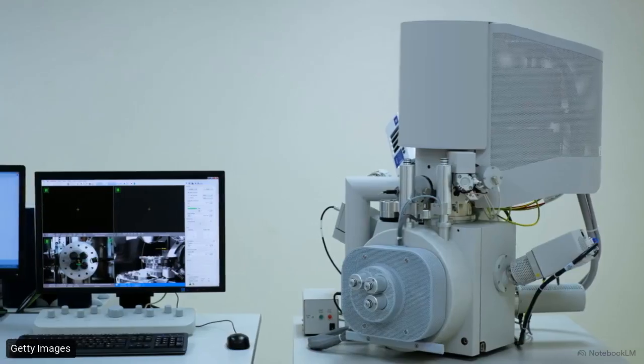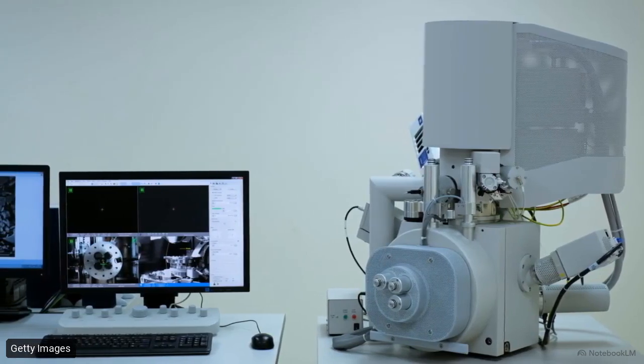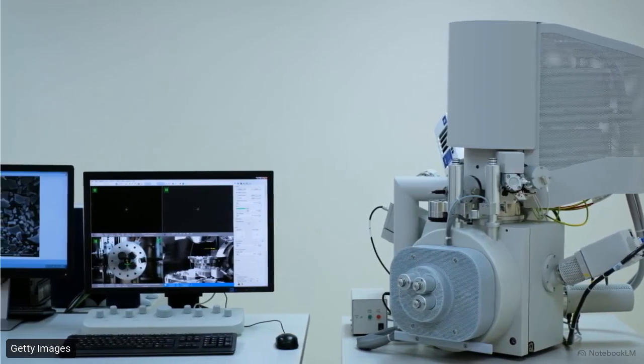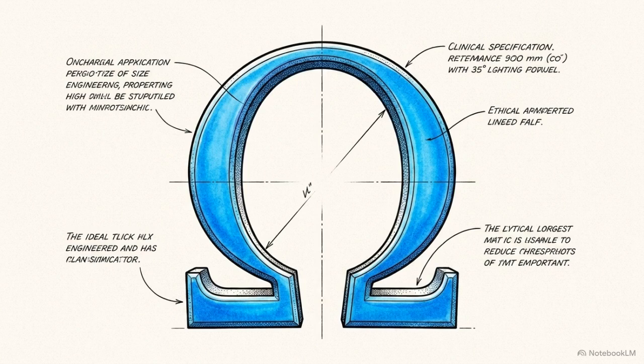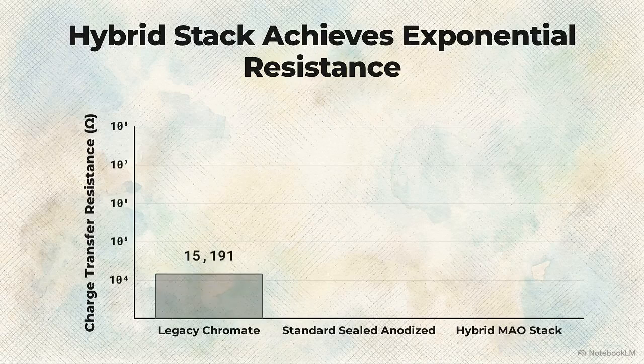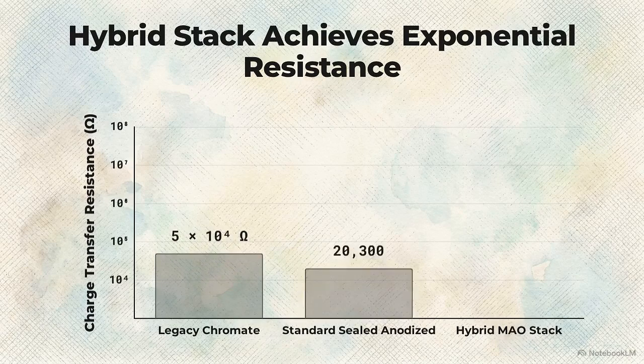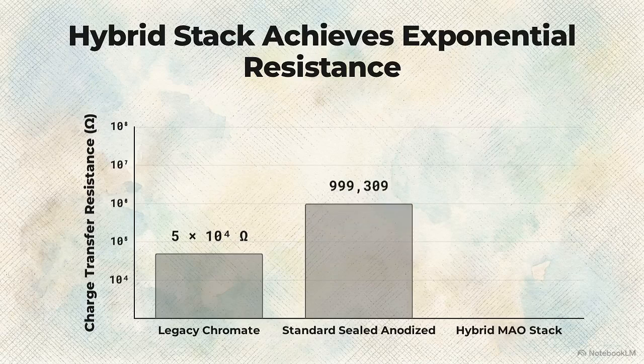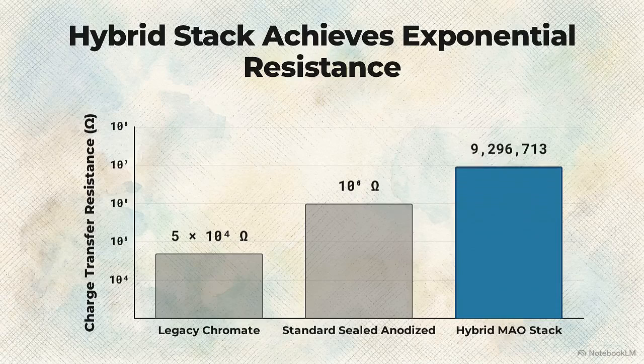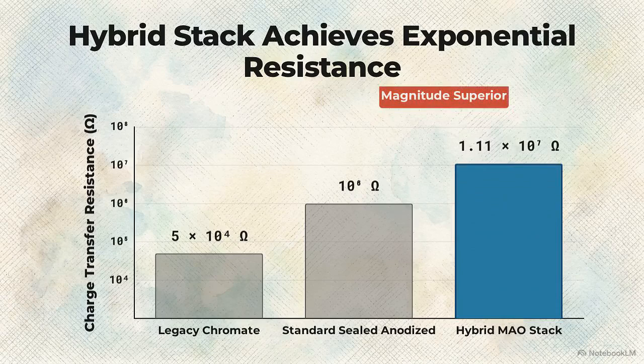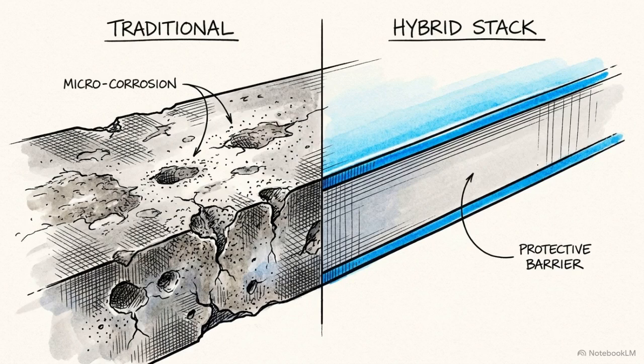We verify the efficacy of this hybrid stack using electrochemical impedance spectroscopy. The quantitative metric for protection is charge transfer resistance, measured in ohms. The legacy toxic standard, chromate conversion coating, provides resistance in the 10^4 to 10^5 ohms range. Standard sealed anodizing performs slightly better, reaching 10^6 ohms. The charge transfer resistance of the hybrid stack reaches 9.3 × 10^6 ohms. This engineered system matches legacy standards and outperforms traditional aerospace protections by 2 orders of magnitude.